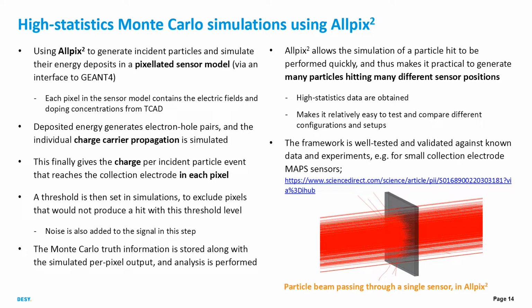So in this way, we can simulate particle hits quite quickly and make it practical to generate many particles hitting many different sensor positions, so we can get high statistics data, and this makes it relatively easy to test and compare different configurations and setups. The framework is also well tested and validated for known data and experiments, for example, for small collection electrode map sensors, which is basically what we use, just in a different technology. Here in a paper by Katarina Dort, this sketch just shows a particle beam passing through a single sensor in Allpix².